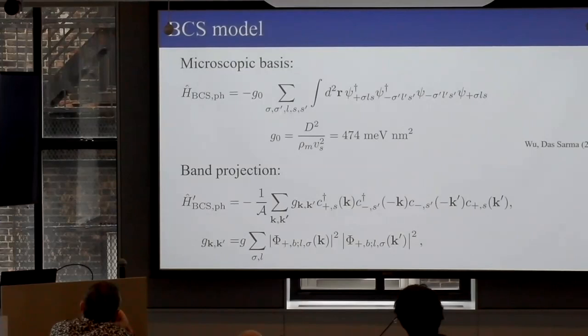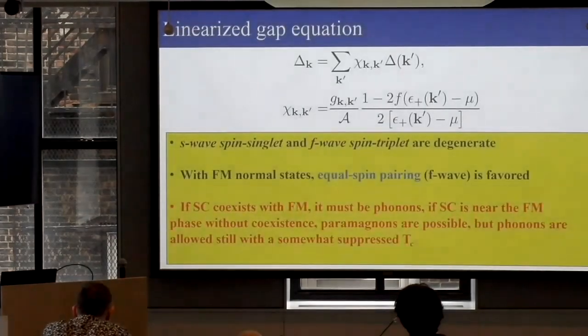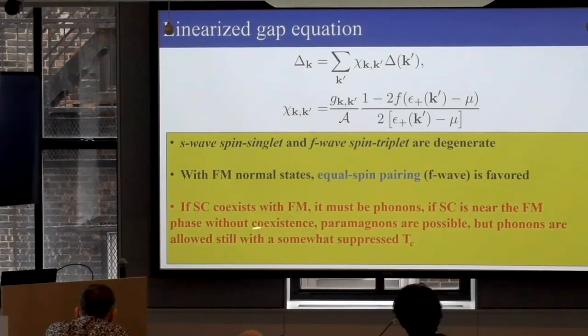So we then do a calculation. Yang-Zi Cho did a huge calculation doing band projection, and then using the BCS approach. I'll come to whether we do full Eliashberg or not. This is a linearized gap equation. I'm still talking about BCS. Then we solved it numerically. And what we find is that superconductivity is actually in the same regime where he's finding ferromagnetism.